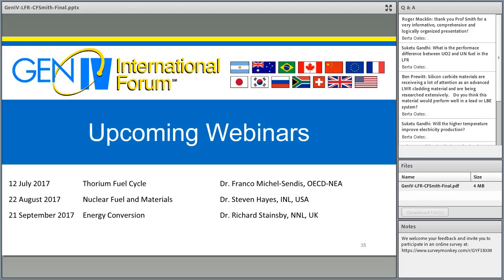And then I would say that there are other systems that are being looked at where oxygen control is not the primary approach. If the temperature is kept low enough, then one can use a coolant that has very little oxygen in it, because the corrosion processes don't really kick in until you get above a certain threshold.